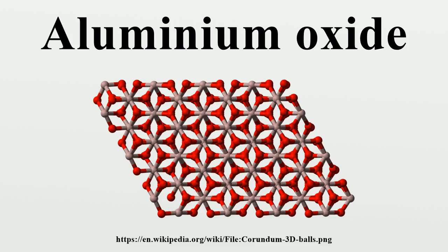For its application as an electrical insulator in integrated circuits, where conformal growth of thin film is a prerequisite and the preferred growth mode is atomic layer deposition, Al2O3 films were prepared by the chemical exchange between trimethyl aluminum, Al(CH3)3, and H2O: 2Al(CH3)3 + 3H2O → Al2O3 + 6CH4.